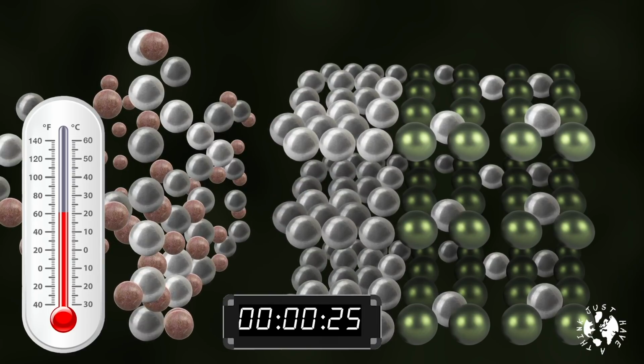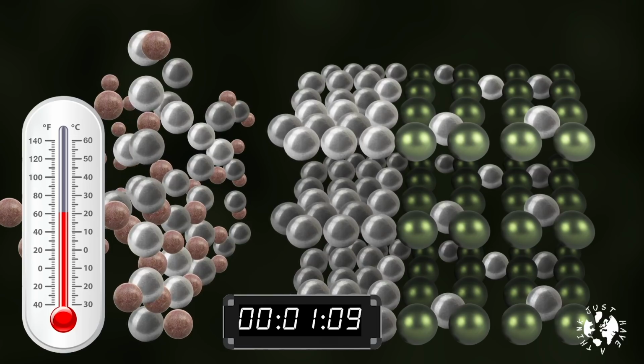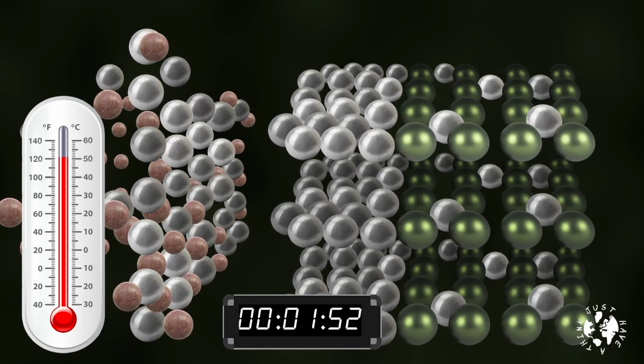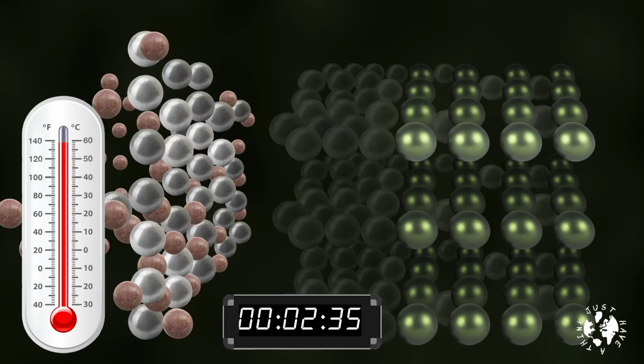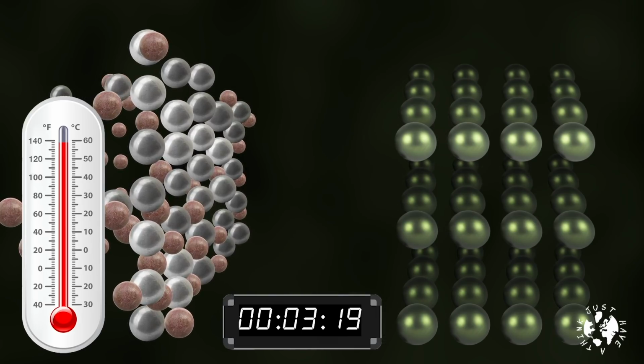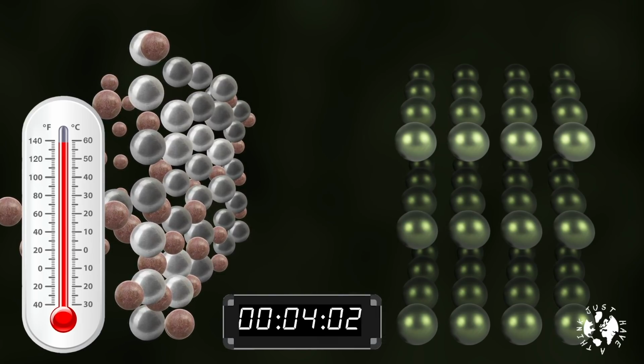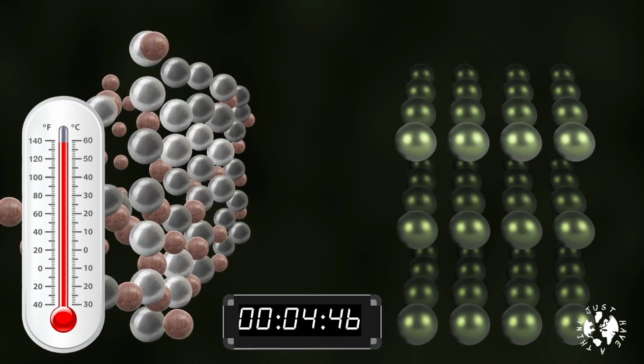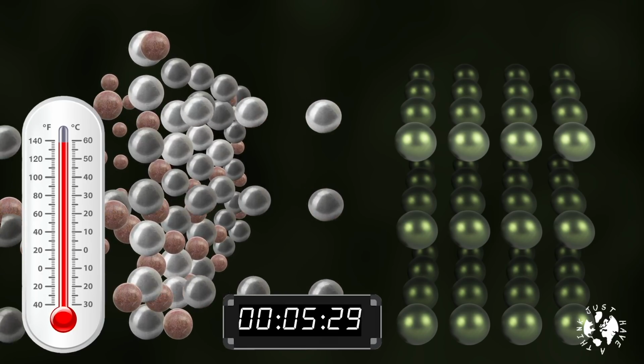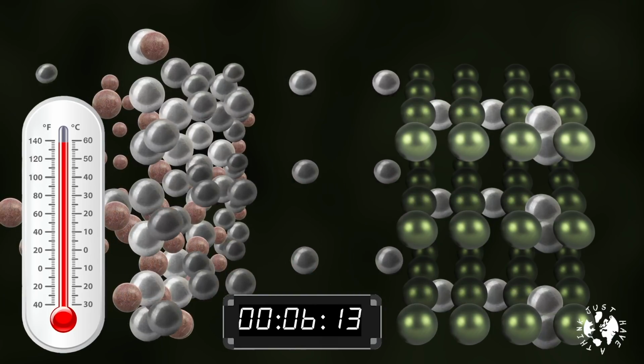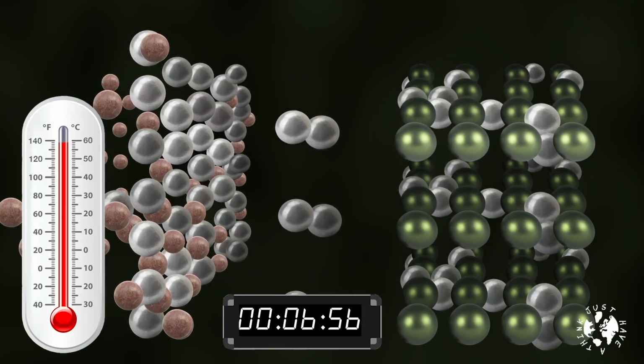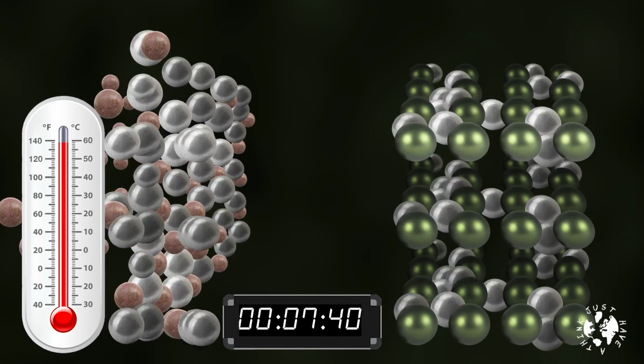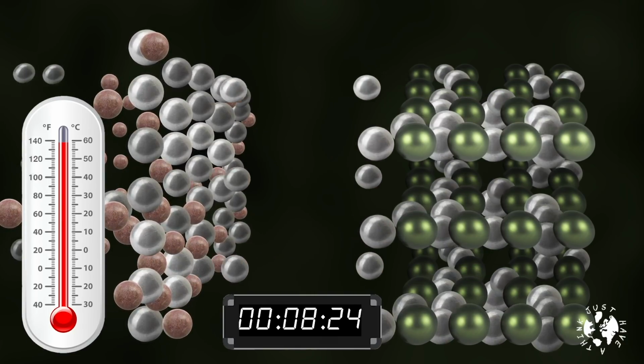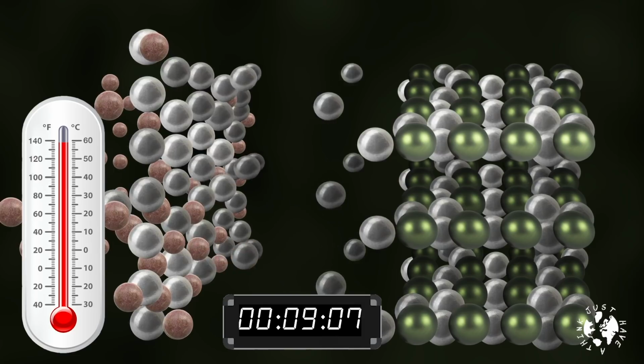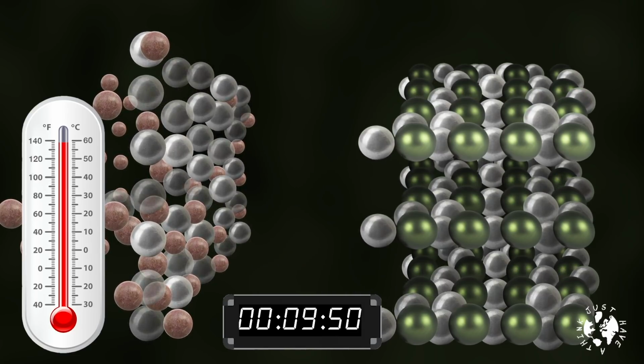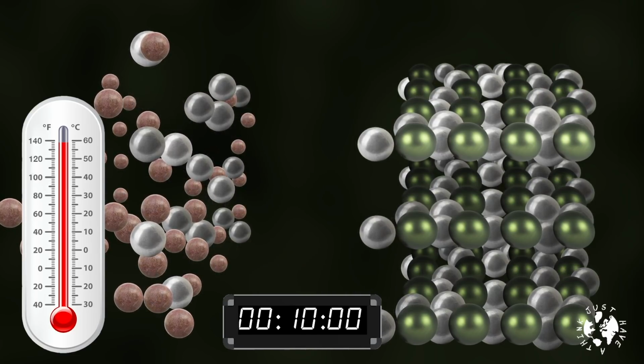The idea is to heat the cell up to a high temperature of about 60 degrees Celsius during the charge stage to prevent the problem of lithium plating, but only keep the cells at that temperature for a short period of time, 10 minutes to be precise, which is the exact amount of time that the Department of Energy has challenged developers to achieve for the full charging cycle. And because that pesky solid electrolyte interphase growth depends on a longer period of charging cycle time, this unwanted phenomenon also gets minimized in a short charge cycle.